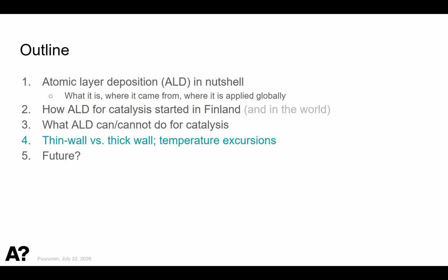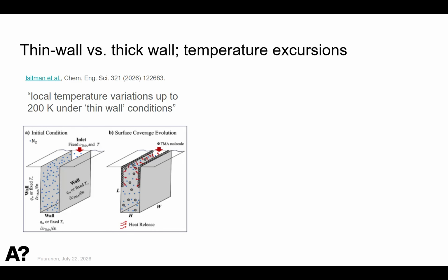And one thing that I didn't have time to talk about in those two presentations that I gave: ALD is based on adsorption, it's based on chemisorption. Chemisorption is exothermic, and ALD reactions are very fast. Good ALD processes are based on fast and aggressive reactions, and that means that heat is being released in significant amounts. Also this year we have a CFD paper out jointly with collaborators from Aalto University, and these CFD calculations were made for cases that are relevant for both the semiconductor field and catalysis or other particle-based fields, and they simulated, so to say, thin wall and thick wall conditions.